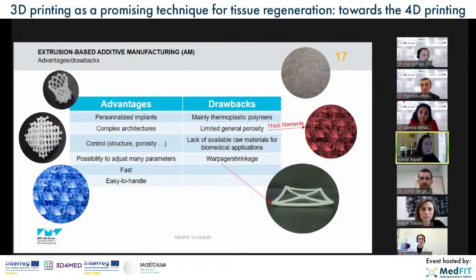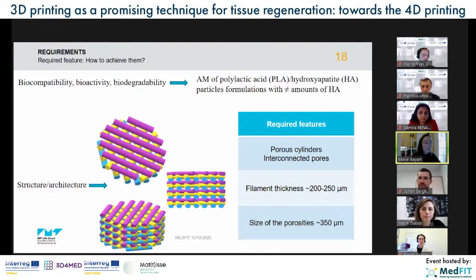So in the next slide, we have requirements, as Marie told you before. So we need biocompatibility, bioactivity, and biodegradability. These features we can reach by using polylactic acid and hydroxyapatite particles that have these features. But for the structure and architectures, we need 3D printing to reach the required features of porosity, interconnected pores, and filament thickness. We need thin filaments, and the size of the porosity also needs to be quite small. We need to reach here 350 micrometers. We found these features in the literature review.